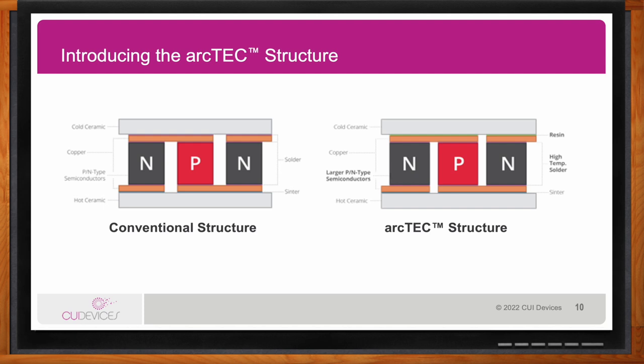And what this is, it is a thermally conductive resin layer on the cold side between the copper and the ceramic. And this absorbs some of the expansion and contraction caused by these large temperature fluctuations, and therefore reduces the stress on the internal components of the Peltier. This thermal stress can cause degradation of performance over time. Well, by adding in the arcTEC structure, the thermally conductive resin layer, we reduce the thermal stress and in turn increase the potential lifetime of a Peltier.